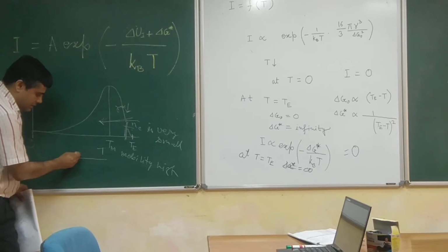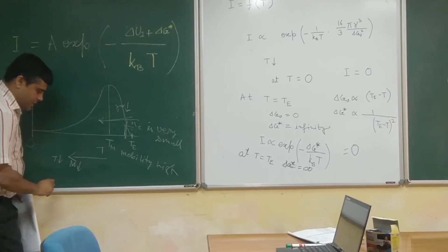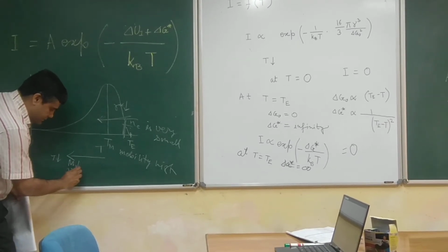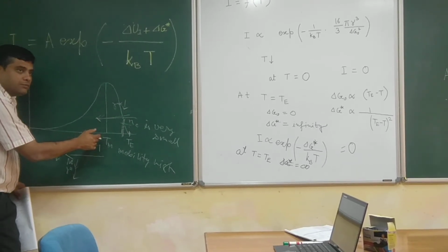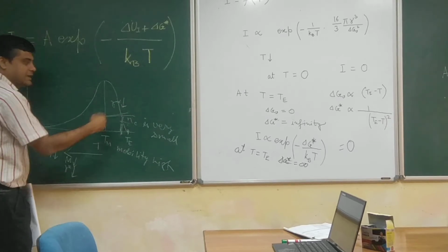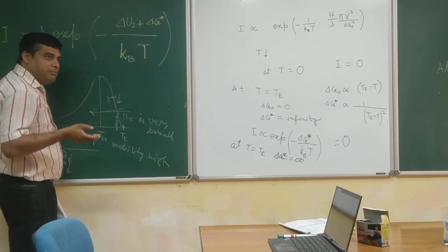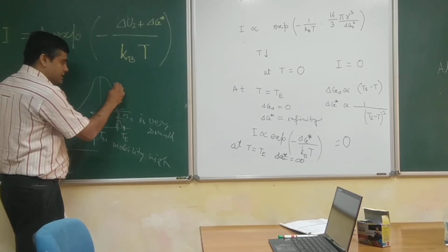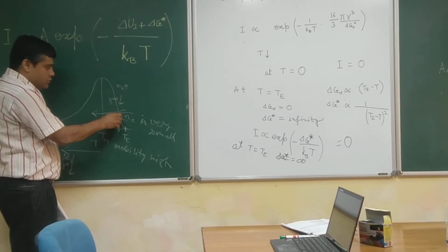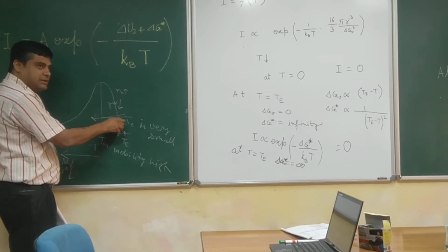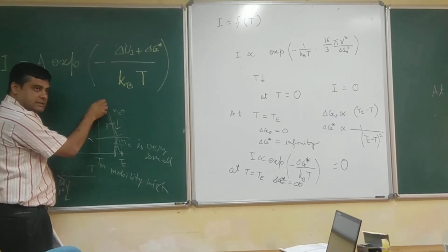As the temperature is lower, your mobility comes down, R star comes down, but at the initial stage R star comes down much faster. So NC, the number of such critical nuclei, becomes very high. So NC going up is faster initially. Even though mobility comes down, NC is still very high, so your nucleation rate increases.